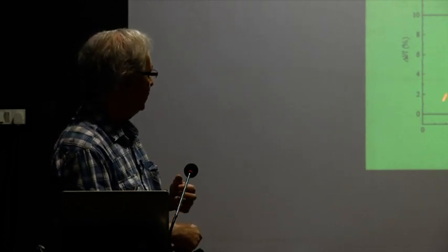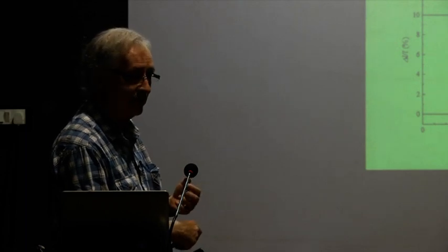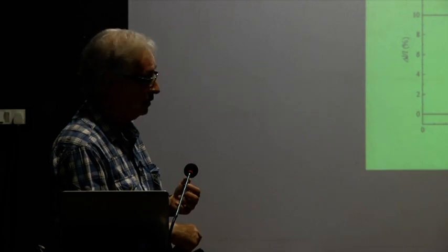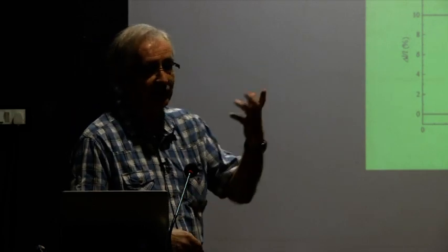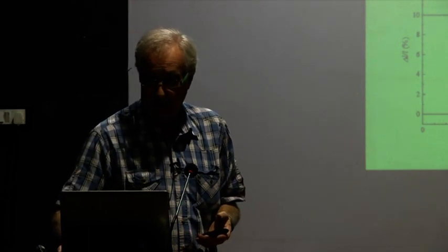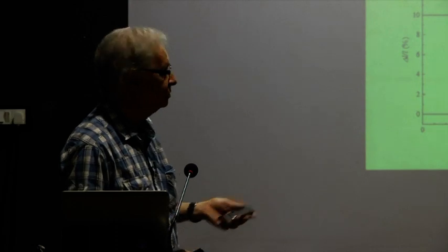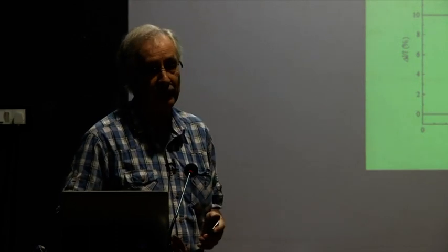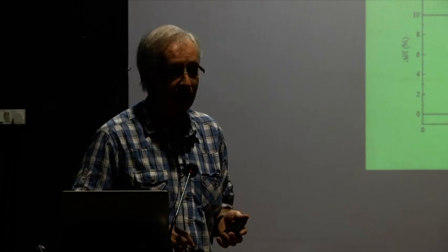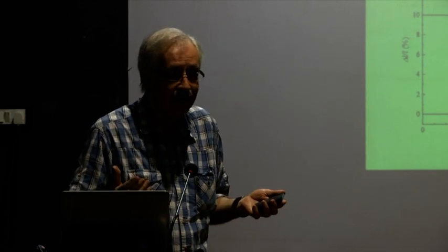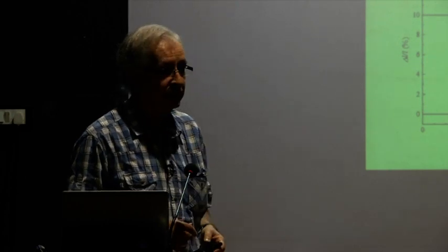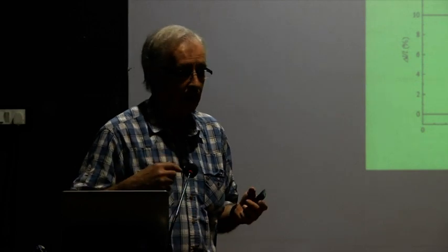And if you measure the length change under a magnetic field, you see that you can change the length of the whole thing by about 10%. Can you put in a load? Yes, to a certain extent, but not as in nickel titanium, because the forces that are involved in this case are very little.